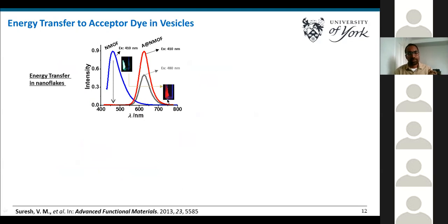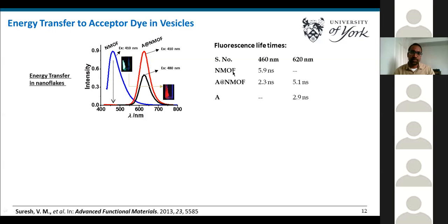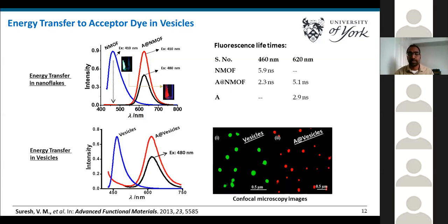This is also evident from direct excitation. When there is an energy transfer, direct excitation of the dye should have a lesser intensity, which we have already seen here. The energy transfer in the MOF structures is also evident from lifetime analysis. When there is an energy transfer, the lifetime of the donor, which is the NMOF, should reduce in the donor-acceptor system. As you see, the lifetime of the NMOF is 5.9 nanoseconds, which is reduced to 2.3 nanoseconds. So this is an indication of energy transfer happening in the system. We have also studied the energy transfer in vesicular nanostructures, as evident from similar fluorescence and confocal images.